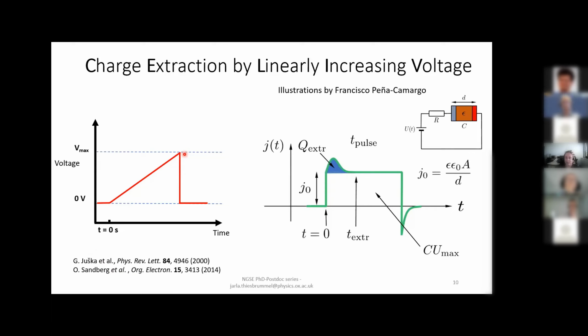Now, the interesting thing about this measurement is that normally you always extract your capacitive charge. So again, the device works as a sort of capacitance, so there is some charge present in the system, and this we initially extract. And this normally would look like a square. In reality, it's not completely square because of the response time of the system, but generally you have your capacitive charge that you can extract with this CELIV measurement.